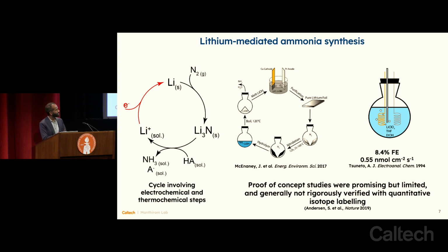What we've been interested in instead is a report from 1994. There was a group in Japan that demonstrated this ability to put two wires into a solution. At one of these wires, a copper wire, you could plate lithium ions to make lithium metal. That lithium metal could then react with nitrogen gas that you're bubbling through, making lithium nitride. It could then react with a proton donor, ethanol, to make the lithium nitride into ammonia. And all that could happen in a single beaker.